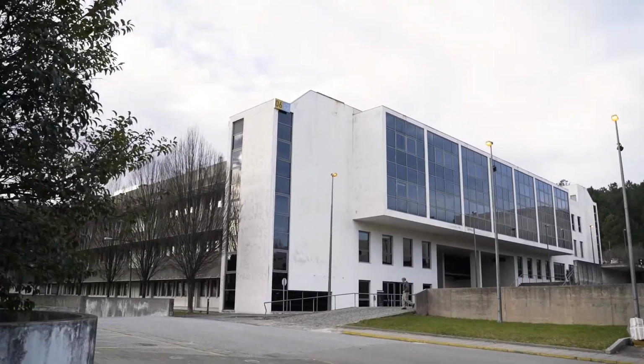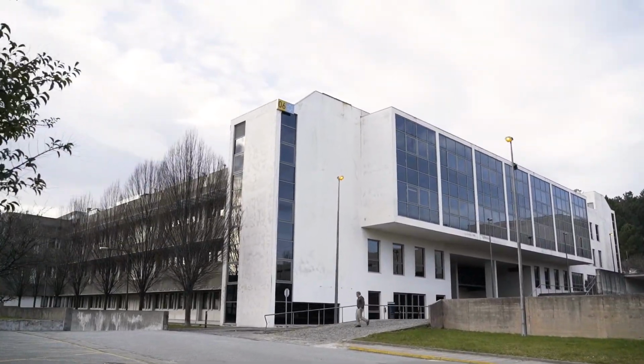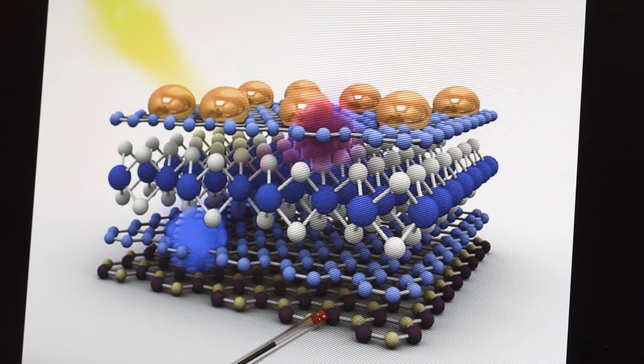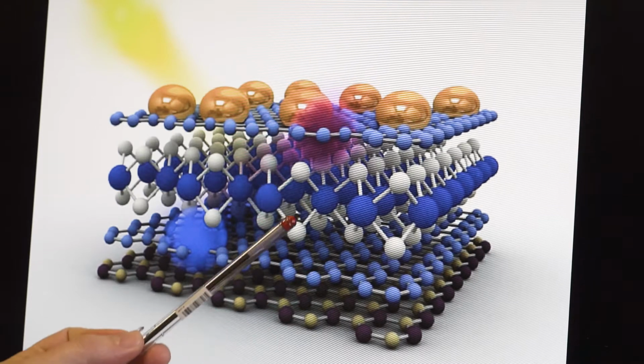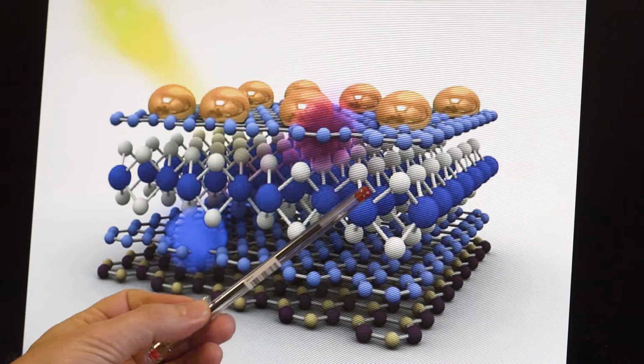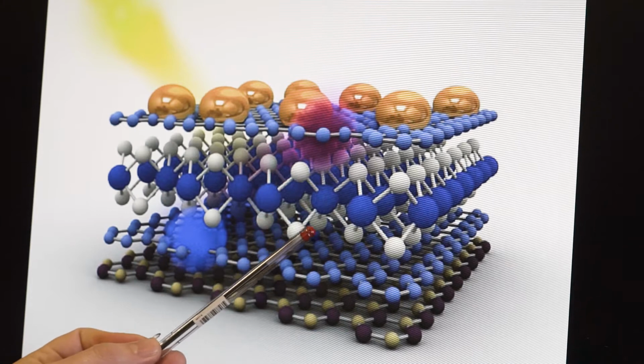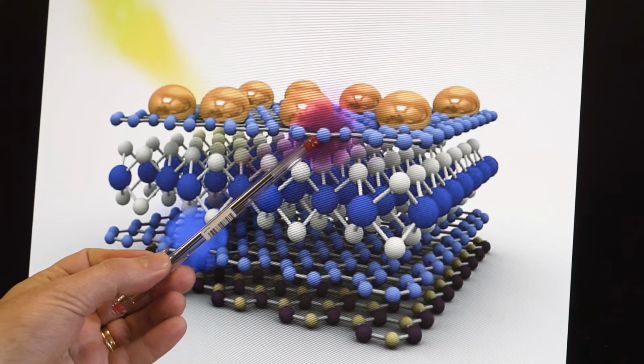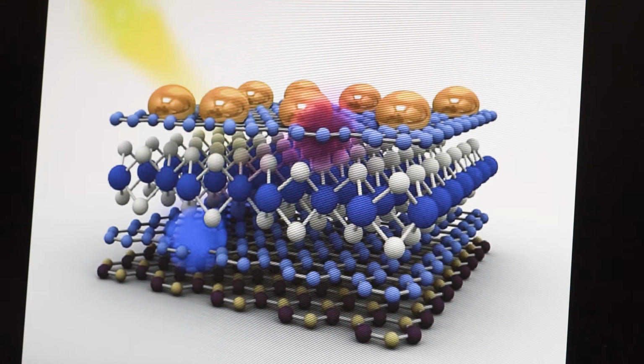The device is represented here on the screen. It's composed of different types of 2D materials. In this case, there are three different types of 2D materials. You have hexagonal boron nitride on the bottom. Then you have graphene here, represented by the blue spheres. In between, the transition metal dichalcogenide is this fairly complicated structure. And on top of it, you have another graphene sheet, and then you have metallic nanoparticles.